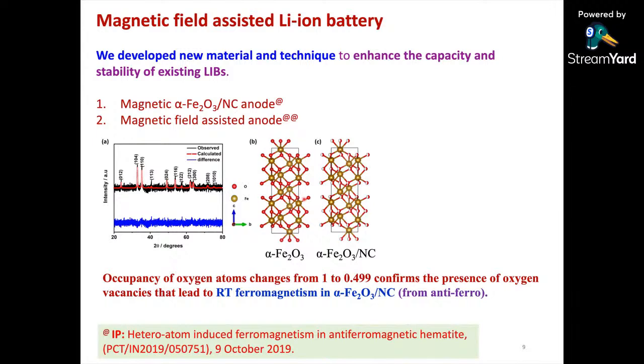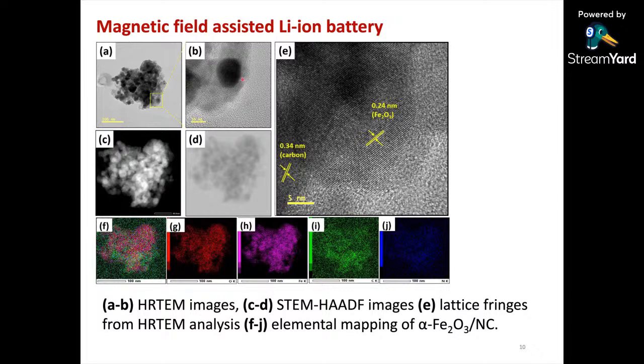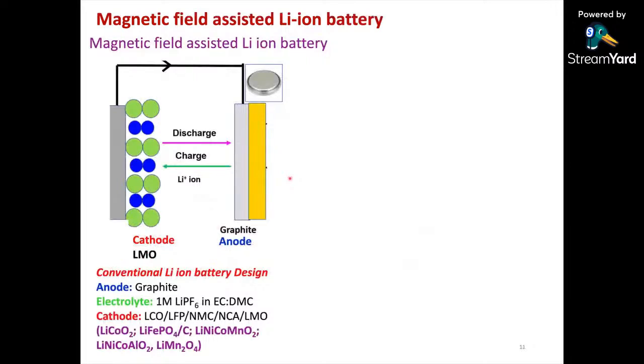So this is alpha Fe2O3, and we prepared the alpha Fe2O3 nitrogen-doped carbon by a simple technique, for which we have already filed IP. There are a lot of oxygen vacancies present, which lead from antiferromagnetism to room-temperature ferromagnetism. You can easily see that the Fe2O3 is surrounded by carbon coating, and high-resolution transmission electron microscopy shows very clearly the lattice planes of Fe2O3 as well as the lattice planes of the carbon-enclosed Fe2O3.